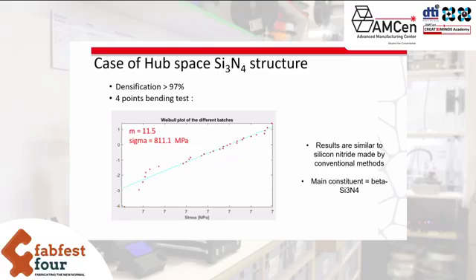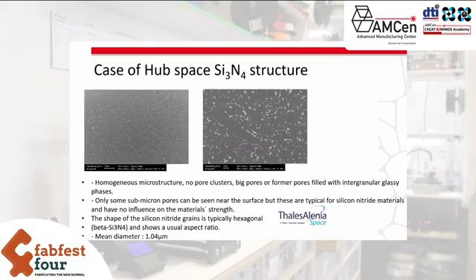You know, it is crucial for all of us to demonstrate that 3D printed ceramics can obtain the same properties as ceramic made with traditional process. It is clearly a key point for the adoption of the process. Then, just a few words about the microstructure of the parts, which confirms what I explained a few slides ago. The pictures taken after sintering show a homogeneous microstructure and no pore cluster. As you can see also, the shape of the silicon nitride grains is typically hexagonal, which is good and typical for beta silicon nitride.